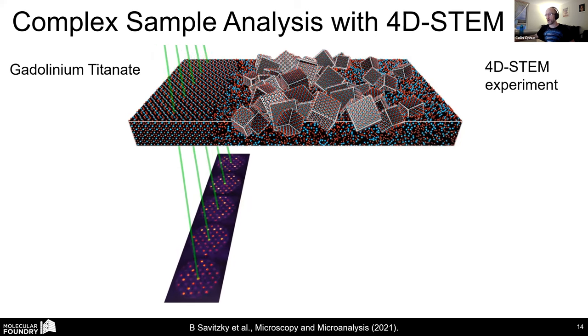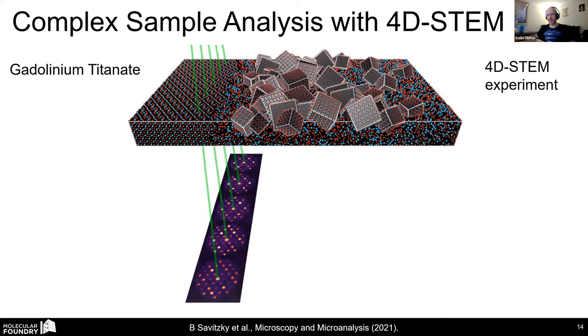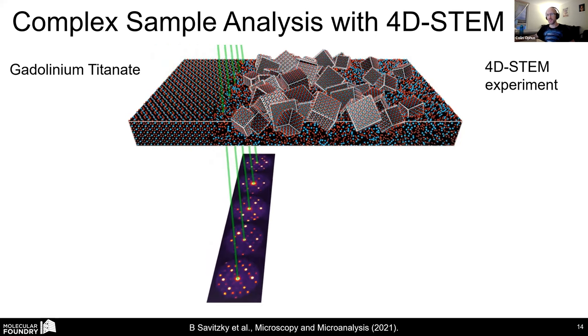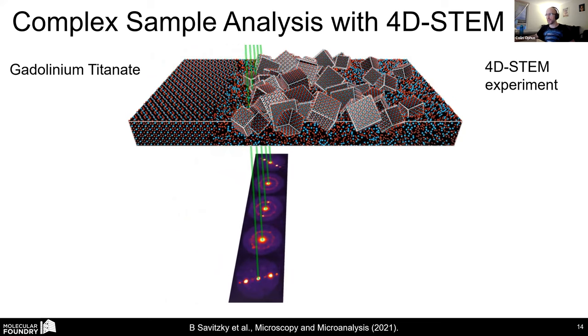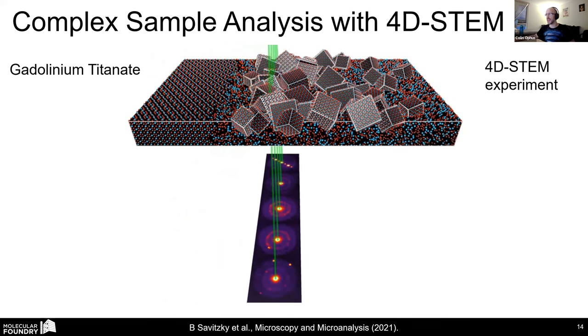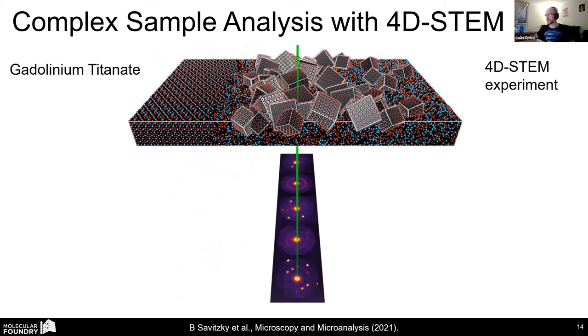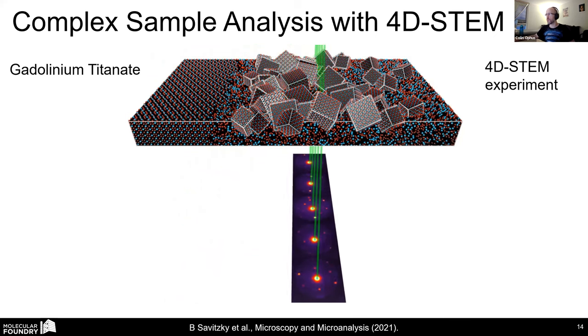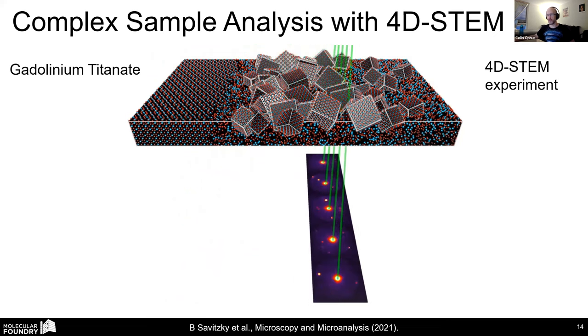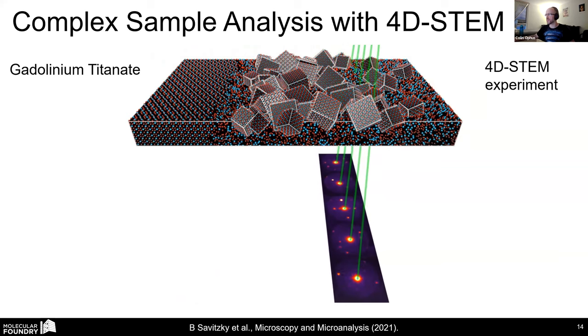And so how do I know that? Well, I know that from the diffraction patterns. We only record one of these images at a time, but I'm just showing the scan of five of these beams as we pass through the material. And you can see these fingerprint crystalline diffraction patterns and characteristic amorphous halos, as I mentioned in the previous slide.